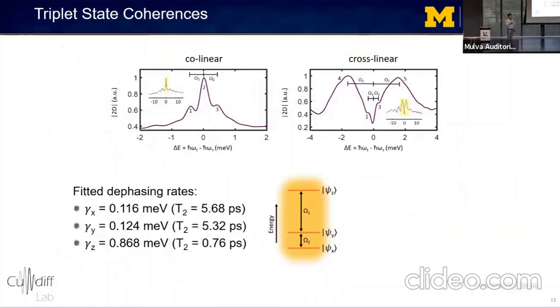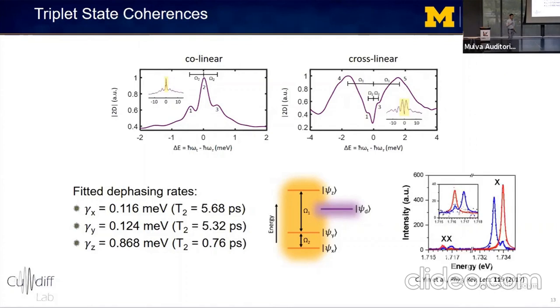So one of the odd features of these slices is that peaks 4 and 5 are much broader than the others. So in fact, when we fit these peaks to extract the dephasing rates of these triplet state coherences, we found that states X and Y shared relatively similar dephasing rates, while state Z dephased much more rapidly than the others. So our hypothesis for why this was the case is that in cesium lead iodide nanocrystals, the dark state actually lies between states Y and Z. And this dramatically increases the dephasing rate of state Z by introducing an additional fast non-radiative relaxation pathway. And this is perfectly corroborated by single nanocrystal experiments of nearly identical samples, where they observed polarized doublets separated by omega 2, but never a third peak separated by an energy omega 1.